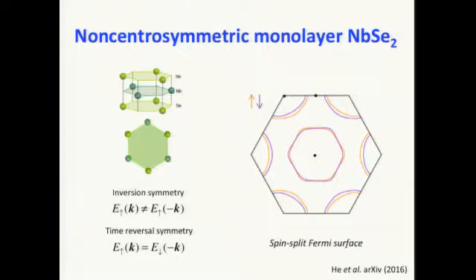However, down to the monolayer case, the inversion symmetry is broken, so the first condition is violated. Here I plot the spin-resolved Fermi surface of monolayer niobium diselenide. The different colors represent spin up and spin down. You can see that at any finite momentum, the Fermi surface is spin split by the spin-orbit interaction.